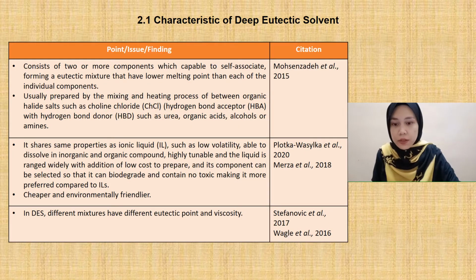So next is the characteristic of deep eutectic solvent. It consists of two or more components which are capable of self-associating, forming a eutectic mixture that has a lower melting point than each of the individual components. And it is usually prepared by the mixing and heating process between organic halide salts such as choline chloride, which is the hydrogen bond acceptor, with hydrogen bond donors such as urea, organic acids, alcohols, or amines.